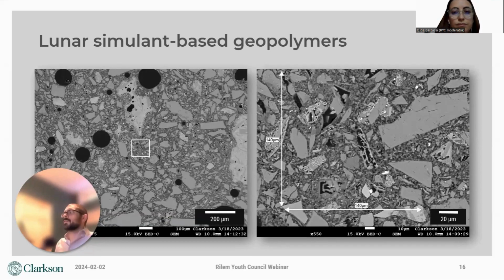Here's a third set of microstructures. This is yet another simulant and activator combination, and this microstructure is really somewhere in between the previous two. We've got a lot of coarse air voids in the image on the left, and in the image on the right, the paste matrix is fairly well developed, but still a bit coarser than the best performing mixtures. So again, maybe we need to increase the activator concentration to achieve better reactivity.